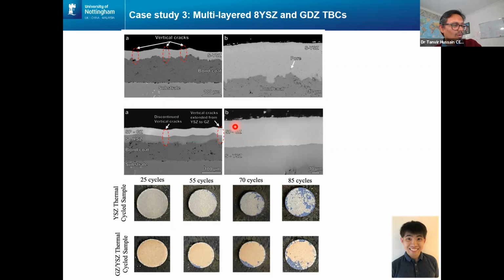Solution precursor, we'll talk about it a little bit later. In suspension spray, we have a particle suspended in a liquid, but in solution precursor, instead of that, we start with a precursor salt. There is no particle in there. That precursor solution decomposes through the flame and ends up as a solid coating at the end. So you bypass this whole route of making powder, suspending the powder in a liquid, and getting a coating. You go from a salt solution directly to a coating.